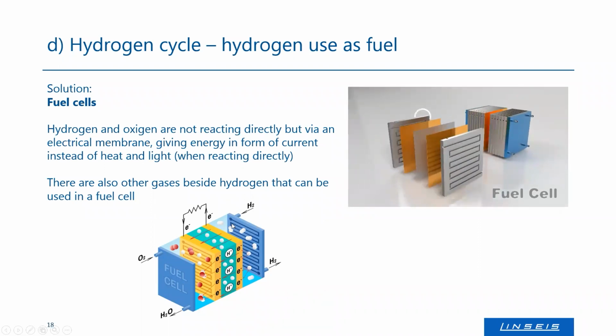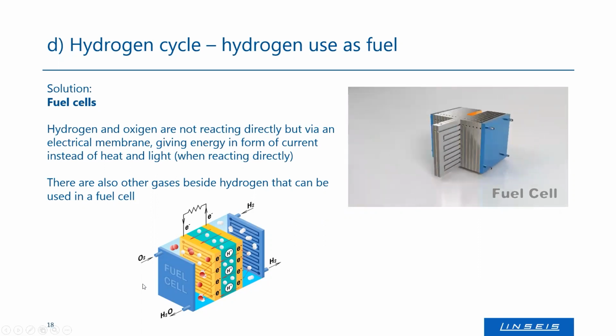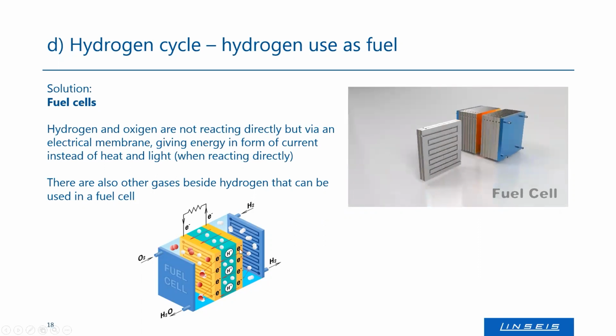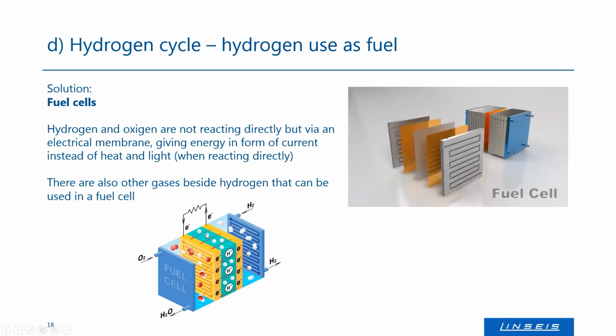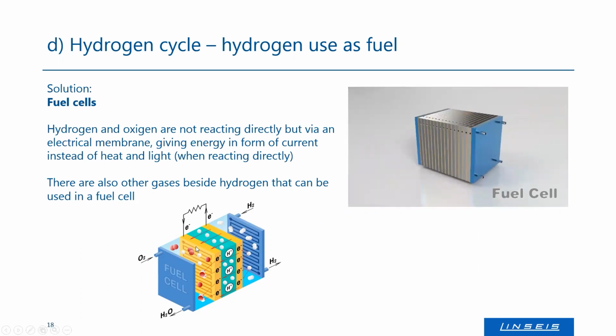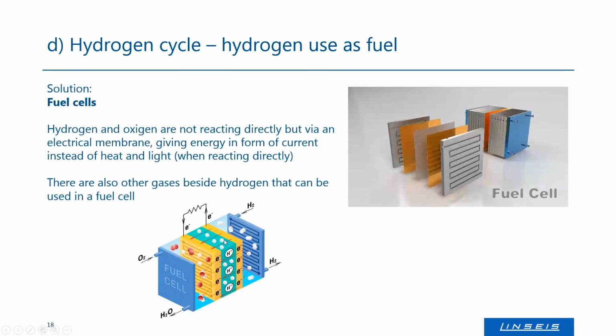That is achieved by this complex structure that consists of two chambers, more or less. One chamber is fed with hydrogen gas, the other one is fed with oxygen. And in the middle of the chamber, there's a membrane. This membrane can be passed by the small hydrogen molecules, but not by oxygen or anything else. So oxygen is hitting the one surface, hydrogen is coming from the other side, going through this membrane, hitting this membrane from the other side.